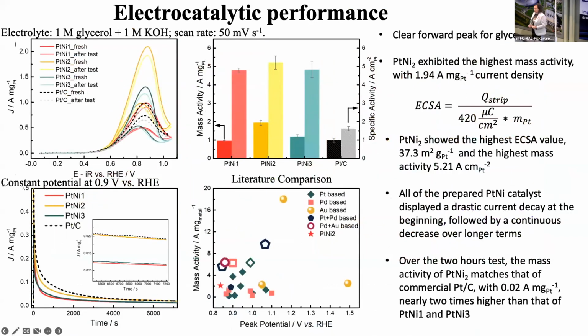Now, I promise I won't show CVs, but unfortunately I have to. So what I want to show here is, well, this is cyclic voltammetry. How many electrochemists in the audience? So basically here, you set the potential and you sweep the potential of your working electrode back and forth, and then you plot the current versus the potential. And so you get peaks, and these peaks mean oxidation or reduction. So you see here that we have a clear forward peak for glycerol oxidation around 0.82 volts.